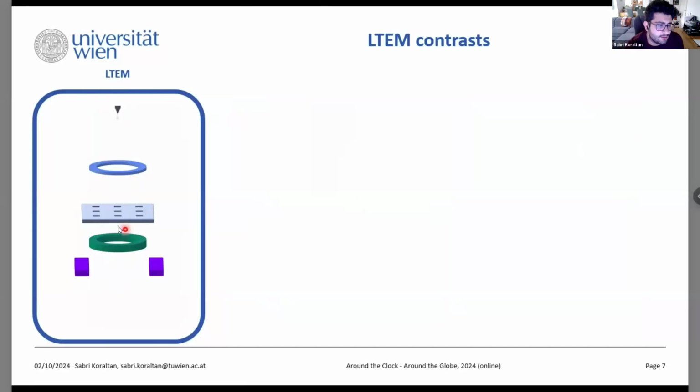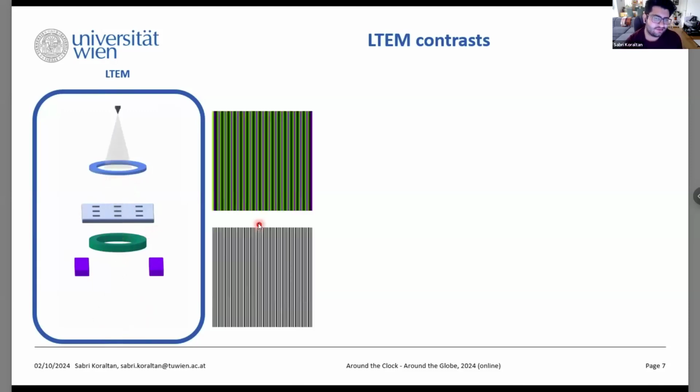of these membranes, and the electron beam can go through, and now the electrons experience a Lorentz force inside the material, and based on the magnetization, they can be deflected, so they will change their direction of movement, more or less. So at the end of the day on the image plane, we actually can obtain some superposition of the beams or some concentration, deconcentration. Let's have a look at what it means in terms of contrast.